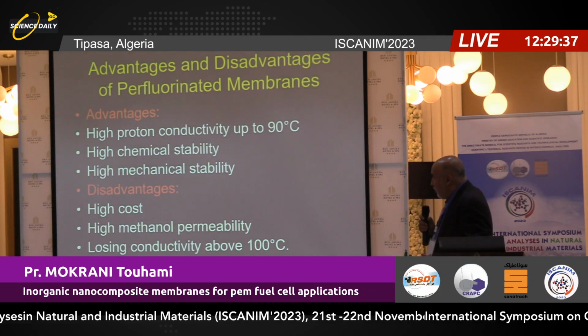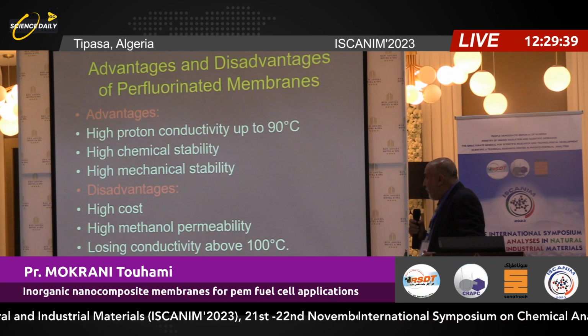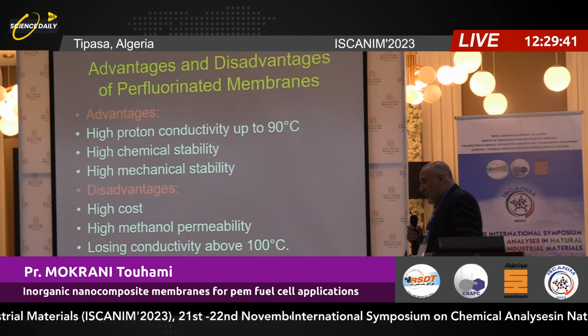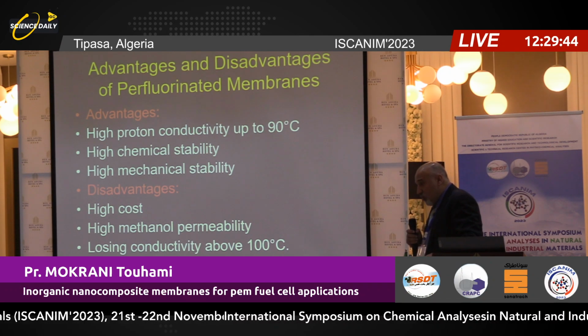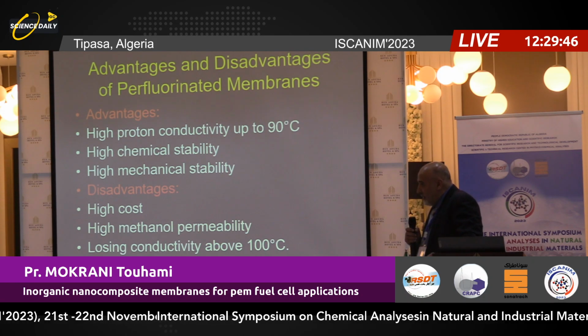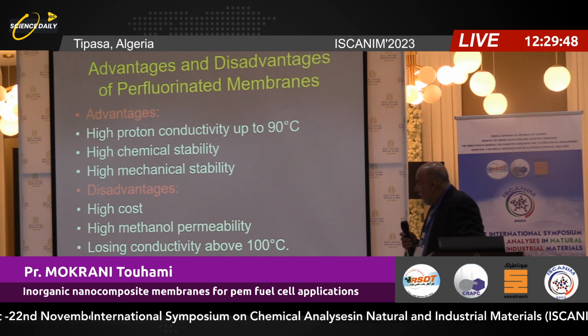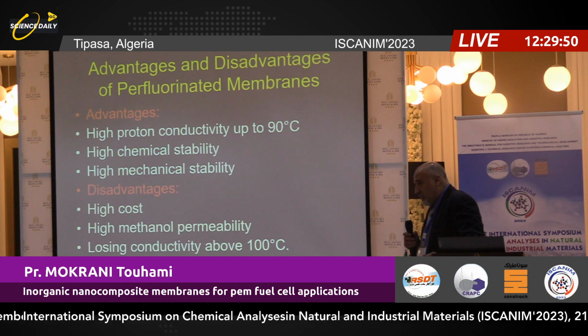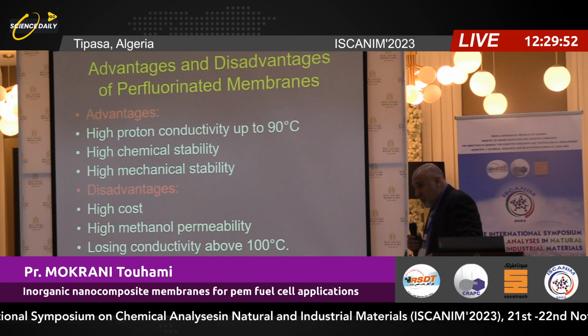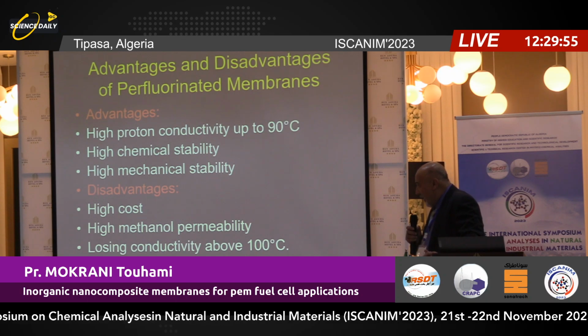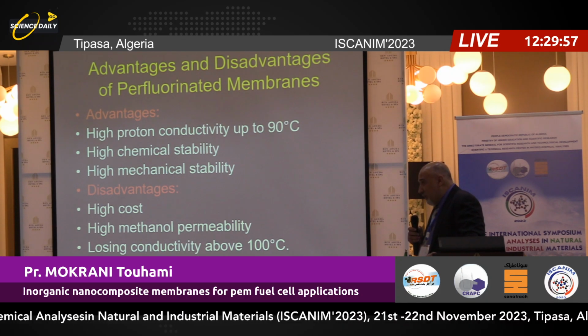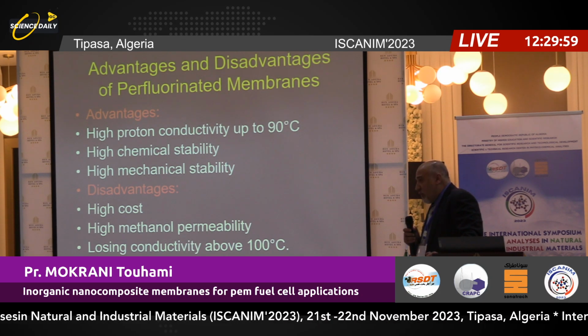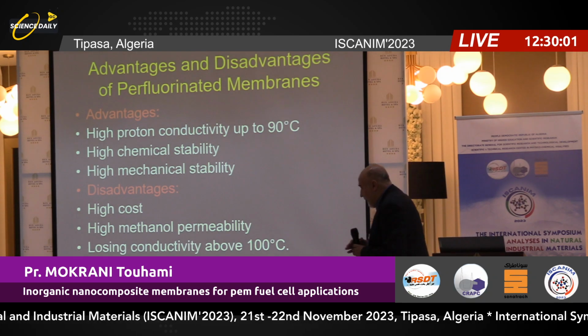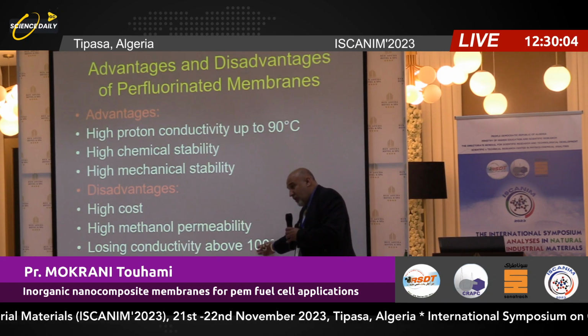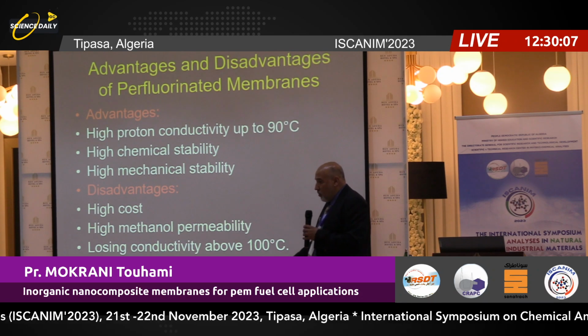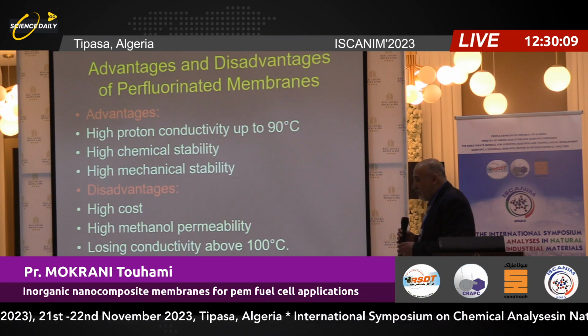So the advantages of Nafion: it's very good. High proton conductivity up to 90 degrees, and the reason is water. So the membrane must be well hydrated. High chemical stability and high mechanical stability. The disadvantages of Nafion are high cost, high methanol permeability, and losing conductivity above 100 degrees. And the reason is water. As soon as it's dry, it loses the conductivity, and you have no fuel cell at all.